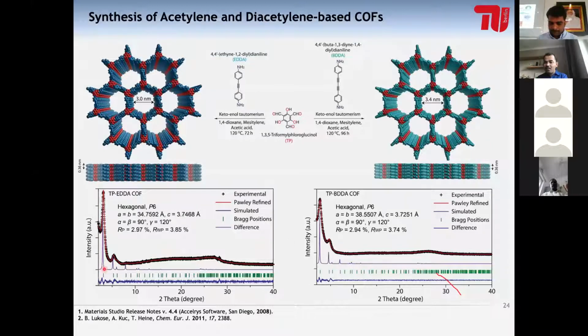And we compared the PXRD patterns of these materials with the simulated structure using Material Studio. And we compared the difference among these two patterns. And what we saw is that there is not much difference between what we synthesized and what we predicted. So from this, we could say that the materials we have synthesized have more or less similar structure like this, with pore size of 3 nanometer for the acetylene-based COF and 3.4 nanometer for the diacetylene-based COF.